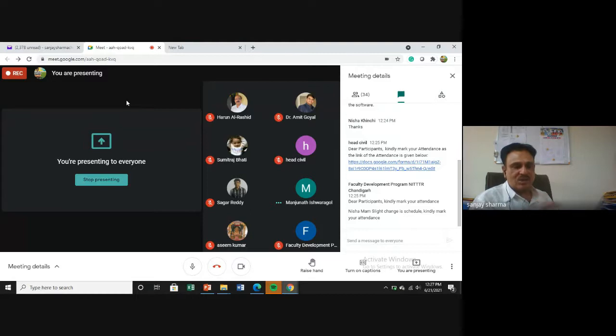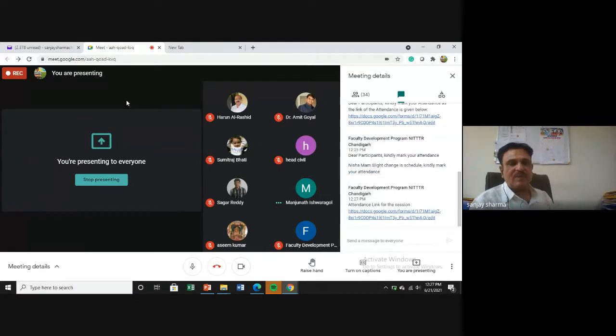But if your carbonation has not reached the bar level, then you can simply provide an anti-carbonation coating on the surface. No need to repair the bar if it is not corroded. Then you prevent further corrosion and further ingress of carbonation, arresting the carbonation at that level. Only if it reaches bar level is it damaging. That is why we provide 50 mm cover, and generally 1 mm carbonation per year is a very normal value. But if it is more than 1 mm, you need to provide some sort of protection. That is how we take the life of a building also. Generally we say 1 mm per year means 50 years, or less than 1 mm per year.